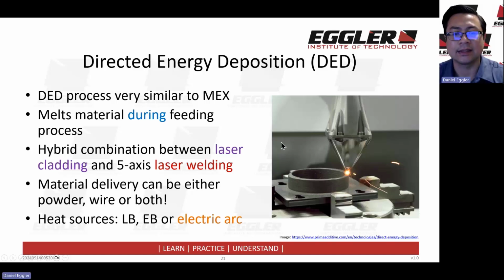As well as a laser CNC, like a 5-axis laser CNC. And the really interesting thing about directed energy deposition is we can have multiple feeds. So we can either have a powder feed, a wire feed, we could have both, we could have different materials. And so what that opens up in an exciting way is you can actually control alloying, all right? So we can actually have different material compositions as we're going through.